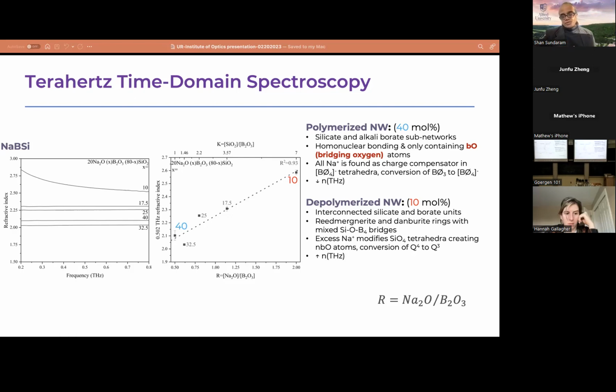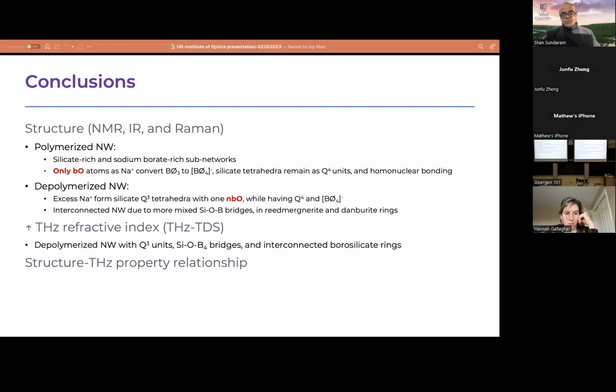So what we have done is we have deconstructed the glass structure and then put it back together and tried to tie it to the optical properties we are able to measure. The conclusion for the borosilicate is that our spectroscopy data all suggest we have a clearly polymerized network and a depolymerized network, and also a mixture of these various units. We still have silica tetrahedra, but mixed with boron rings and borate tetrahedra, and there are sub-network units. That's what constitutes the structure we're looking at.